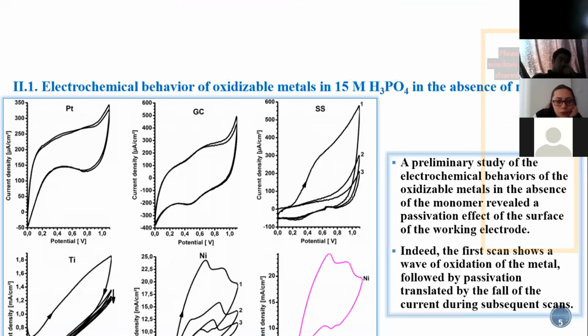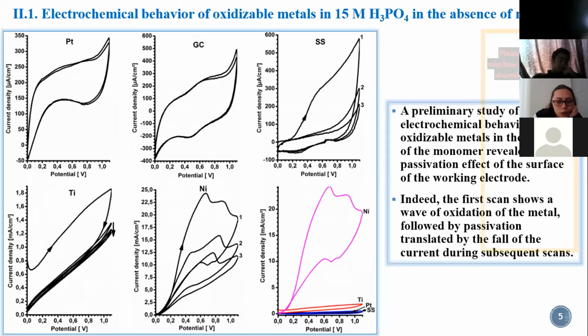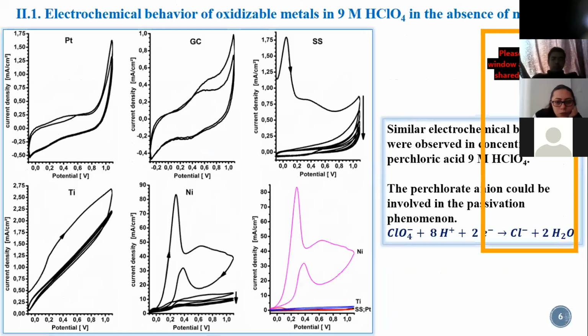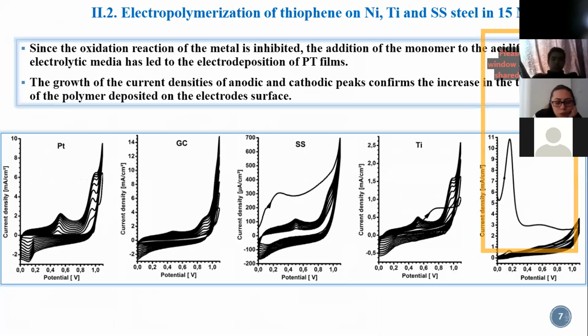A preliminary study of electrochemical behaviors of the oxidable metals in the absence of the monomer reveals a passivation effect of the surface of the working electrode, and the first scan shows a wave of oxidation of the metal followed by passivation. Similar electrochemical behaviors were observed in concentrated perchloric acid, and perchlorate anion could be involved in the passivation. Since the oxidation reaction of the metal is inhibited, the addition of the monomer to the acidified electrolytic media has led to the electrodeposition of polythiophene.